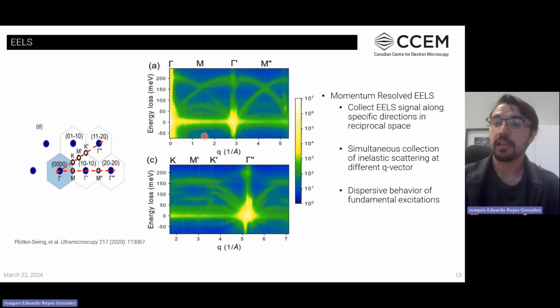When we're doing these kind of experiments, we do sacrifice a little bit of the spatial resolution, but we're still in the nanometer range. So we are able to perform both spatially and momentum resolved EELS experiments with high energy resolution, which allows us to unveil phonons and also other fundamental excitations such as plasmons. There's some hypothesis of even exploring magnons.